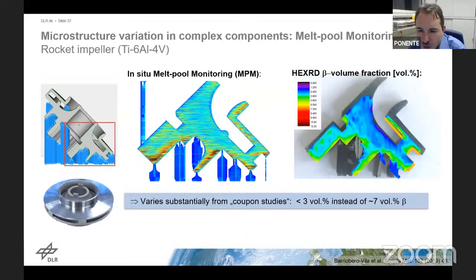And to understand this question, we again went for high energy X-ray diffraction in this case. On the left-hand side, you now see again the MPM cross-section of the data from the pyrometric monitoring. And on the right-hand side, the beta volume fraction across this part of the impeller, where you have the amount of beta phase on the scale on the top.